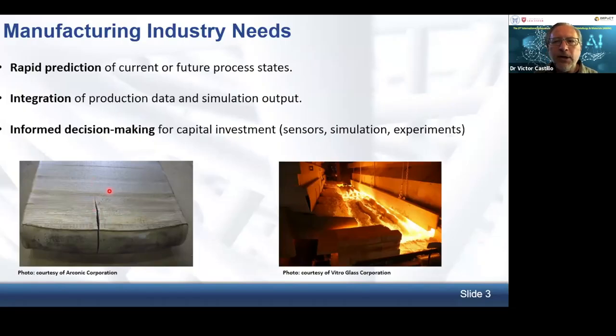And this is a very big problem for the industry, in that the end would have to be cut off, that material would have to be reworked, and then they would have an inconsistent sized ingot for rolling, because they can't send this ingot as is into the rolling process with that crack. Additionally, there could be cracks on the surface, and those would have to be manually machined off. So this could be very labor intensive. So preventing these cracks, preventing the residual stress, is part of the project.